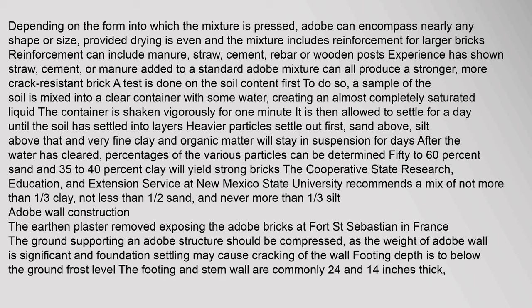The Cooperative State Research, Education, and Extension Service at New Mexico State University recommends a mix of not more than one-third clay, not less than one-half sand, and never more than one-third silt.